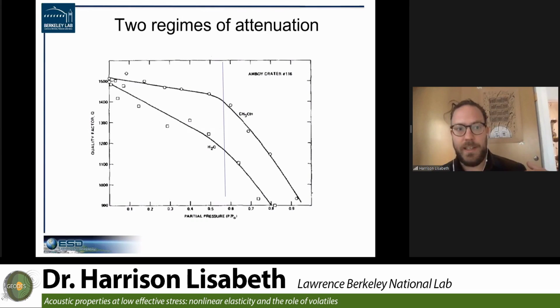But it's not just polar or nonpolar, it also has to do with specifics of the chemistry of the molecule. So here is the quality factor versus partial pressure for water and methanol. And you can see that there's slightly different behavior, which has been attributed essentially to the dipole moment of the molecules, again, having to do with the dynamics of adsorption of the molecule to the surface of the materials.